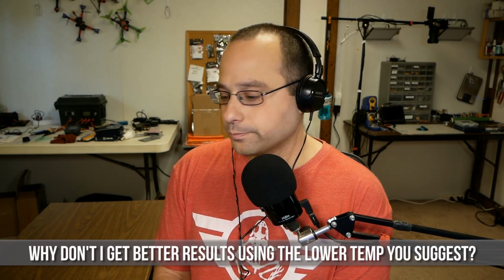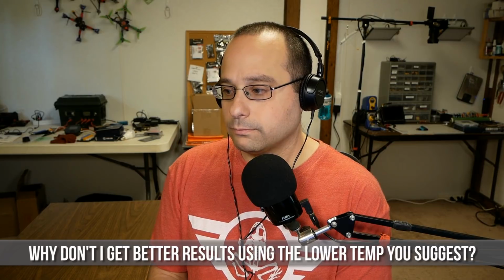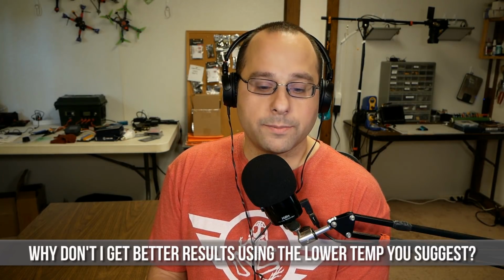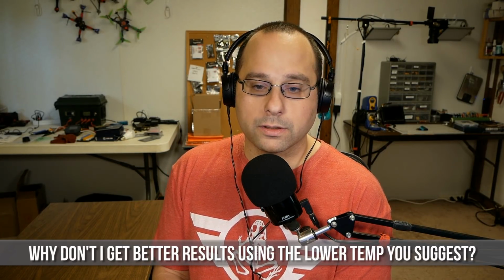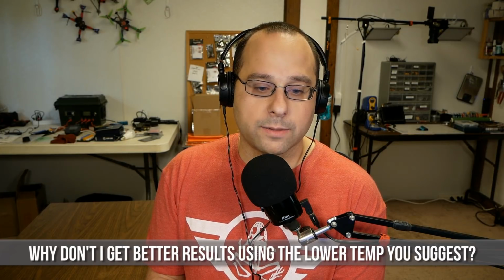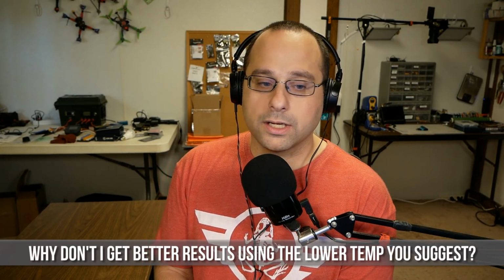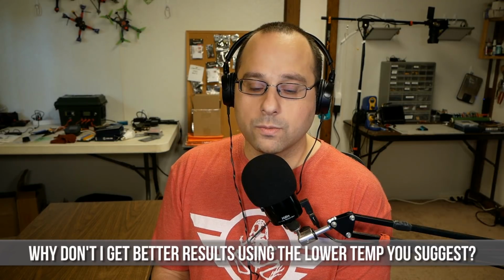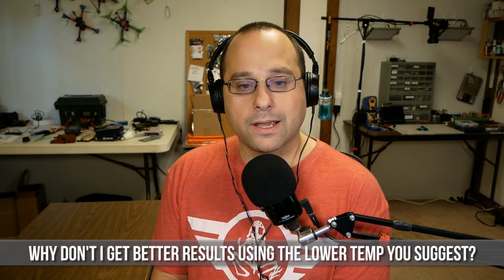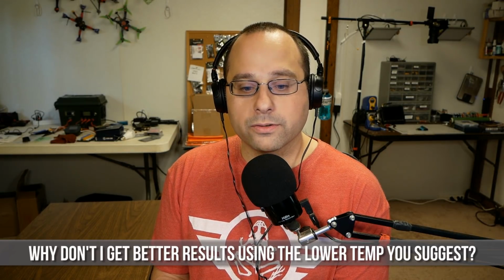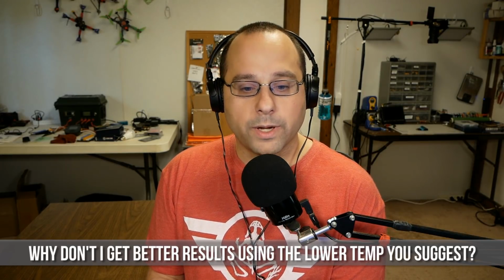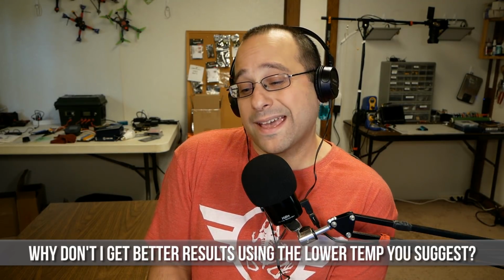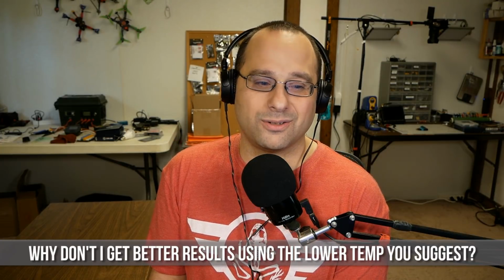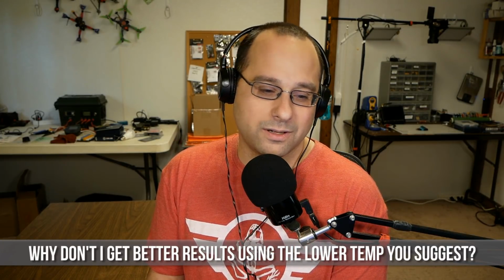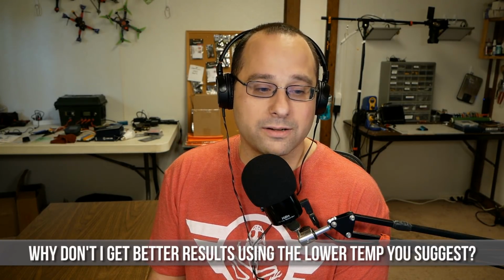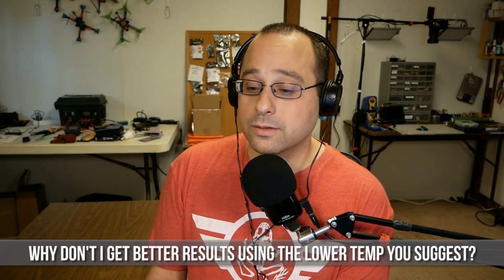Right. So if you're soldering a board or soldering wires? Typically soldering wires to a board, 22 gauge up to maybe as high as 12 gauge. But even on the smaller gauge wires, it just kind of felt like I was in and out faster and got better flow on the solder by using the higher temperature. I didn't get bad results with the lower temperature. It just took longer to finish the joint. I was like, well, why not just run at a hotter temperature and get in and out faster? Maybe that's the question.